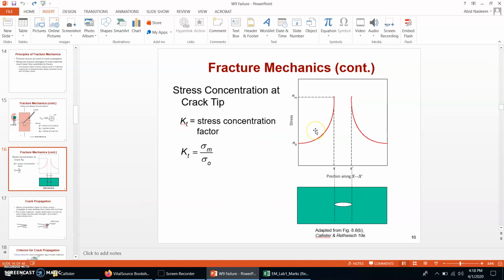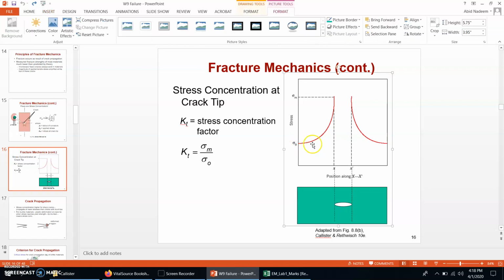This slide shows the variation of the stress. For example, if you have this internal crack, the stress at this crack is equal to sigma m, and then that stress gradually decreases, at the surface of the body, to sigma naught. So there is a variation of the stress. The highest level of stress is at the crack tip, which reduces to the normal stress sigma naught at the surface.